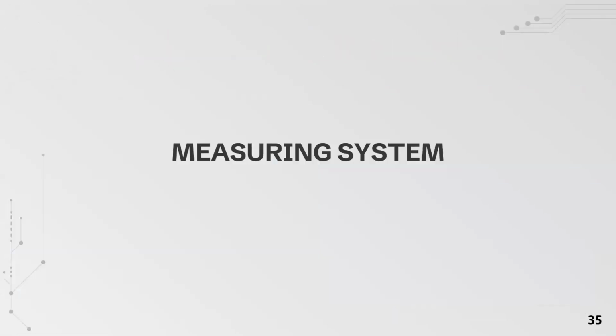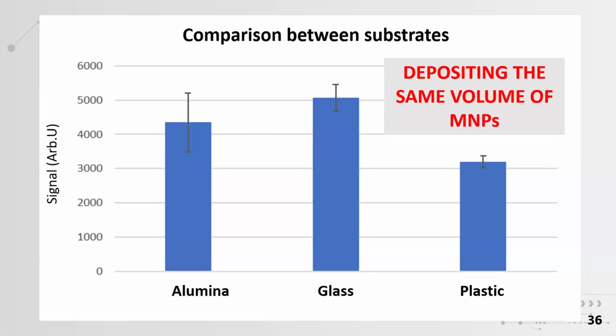So first, we deposited the same volume of magnetic nanoparticles on top of the 3 substrates and obtained these results. As you can see, the clear winner is glass, followed by alumina and plastic. But although the best result was glass, we decided to use alumina instead to perform the calibration because it didn't break easily, and also because the magnetic nanoparticles attached more to its surface.